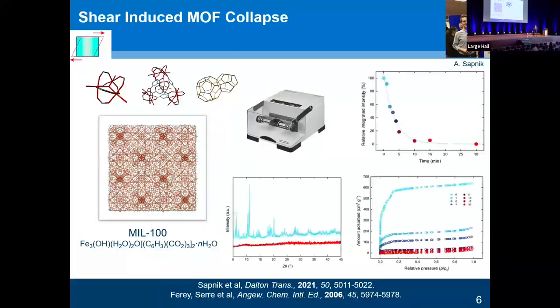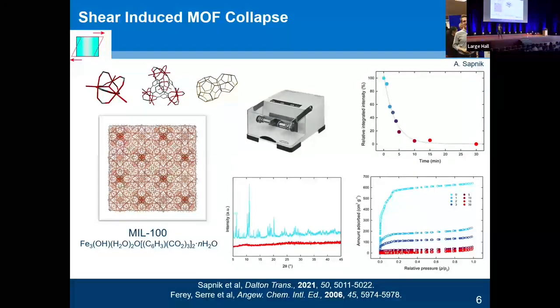What Adam found is actually when you ball mill it, so when you apply shear stress, it collapses very quickly from our Bragg diffraction into something which is amorphous, so no Bragg diffraction. Adam then integrated the intensity of these peaks and found a rough measure of crystallinity. After 1 minute, things are sort of stable in terms of your crystallinity, and then it collapses very quickly to 10 minutes. And it's really interesting to note that that is slightly at odds with its gas sorption behavior. This is N2 gas sorption, where after 1 minute, most of it's already lost. So there's definitely a disconnection between crystallinity and properties.